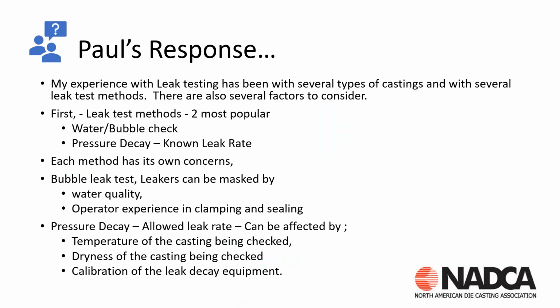And then the other type of leak mechanism is going to be pressure decay. And this is dealing with a known leak rate. So with this type of leak testing equipment, you've got to have either a casting or a master part that you put in there, and it's got a calibrated leak unit on it. So it has a calibrated leak device, and you then check that unit every day and verify that it's measuring the same leak rate.